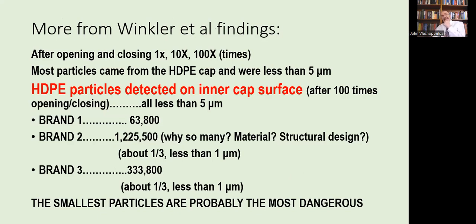One thing that is very interesting is this one right here: one brand of bottled water had about 64,000 microplastics on the inner cap surface after opening and closing 100 times. Now, brand 2 had 1.2 million microplastics on the inner cap surface detected. Now, the third brand, as you can see, 334,000 roughly. And one third of them were less than 1 micron.